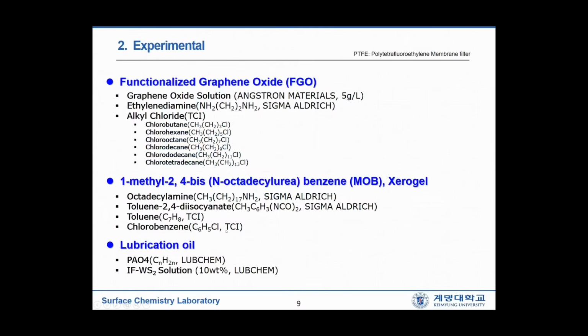This is the experimental part. In order to synthesize functionalized graphene oxide, we have used graphene oxide solution, ethylene diamine, and alkyl chlorides, 6 kinds of alkyl chlorides. We have also used octadecylamine, toluene 2,4-diisocyanate, toluene, and chlorobenzene. We also employed PAO4 base oil and IF-WS2 solution.